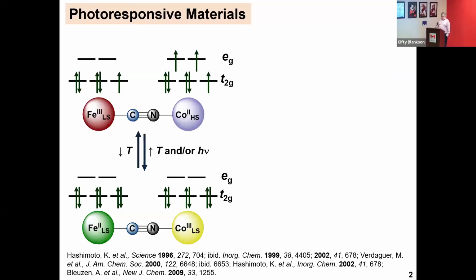And so when you get the synthesis and the conditions just right, and you have an average N5O coordination environment around the cobalt, you have a proper ligand field. If you assume everything's octahedral geometry, you have non-bonding t2g symmetric orbitals. That's the dxz, the dyz, and the dxy. Those are non-bonding with respect to metal-ligand bonding. The eg set are anti-bonding with respect to metal-ligand bonding, and these are composed of the dx squared minus y squared and dz squared.